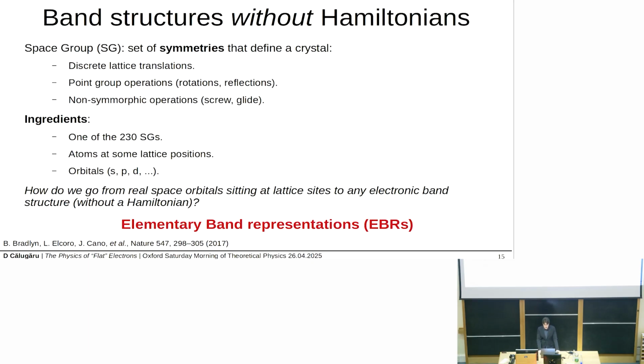you lean on symmetry, because crystalline materials are defined by a symmetry group, right? Something called a space group, which encodes all the allowed symmetry operations. You have translations, rotations, reflections, and such. Given a space group, you need to add only 2 more ingredients to fully characterize a crystal: the positions of atoms within the unit cell, and the orbitals that each atom contributes to the band structure.